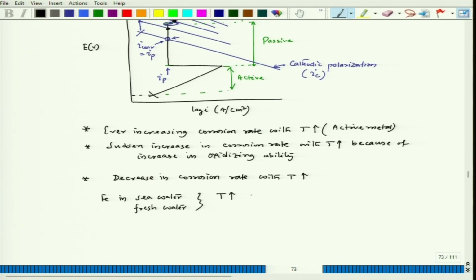With increase in temperature, dissolved oxygen is removed actually. As temperature increases, dissolved oxygen concentration decreases, and we know that oxygen is basically the oxidant which actually gets reduced, and that is the reduction process. It can be O2 plus 2H2O plus 4e equal to 4OH minus. So, if this concentration decreases, the reaction would not go at a higher rate, and definitely the corrosion rate also would decrease. So, it is basically the de-aeration effect of the medium or the electrolyte. There could be a possibility of decrease in corrosion rate because you are removing the active oxidant from the medium or the electrolyte.